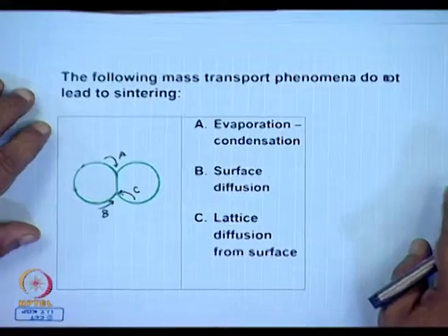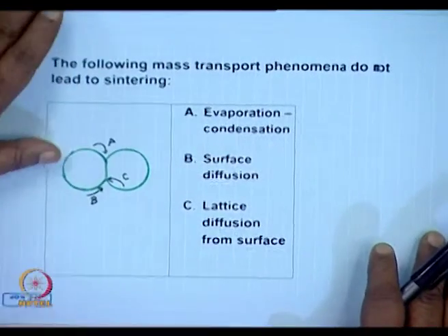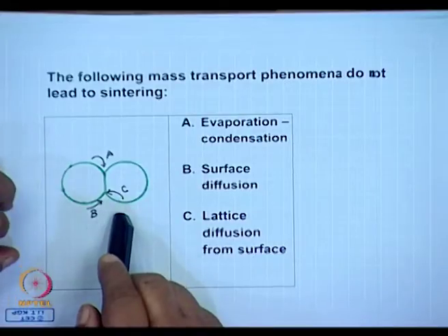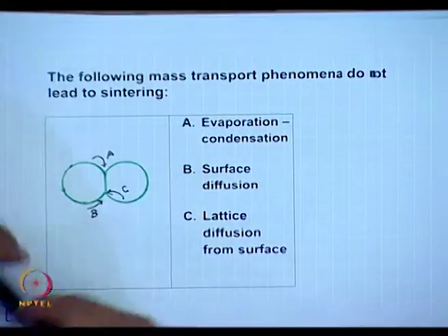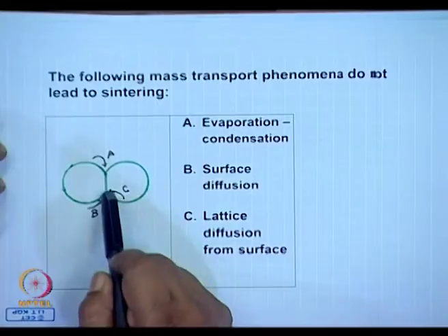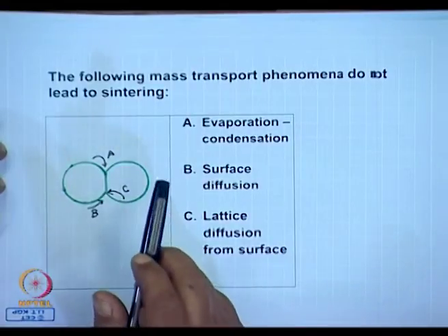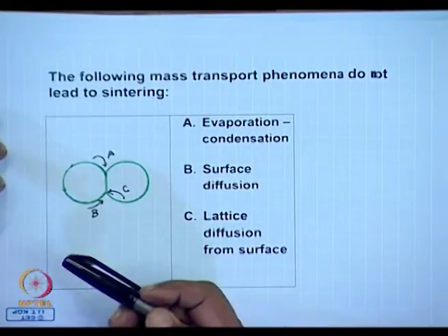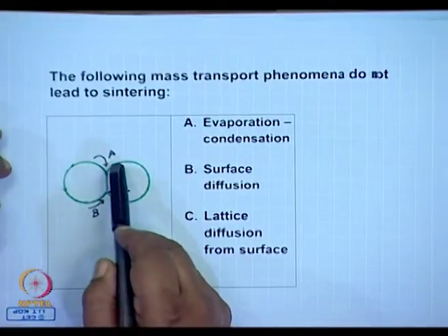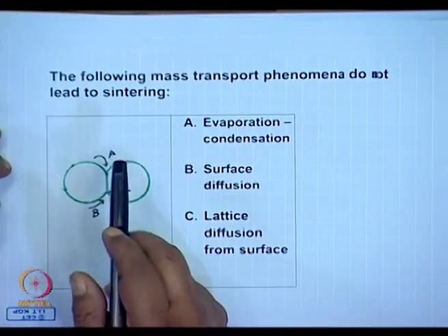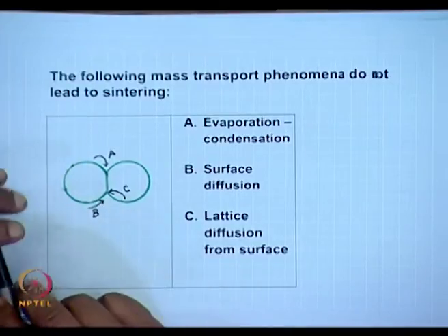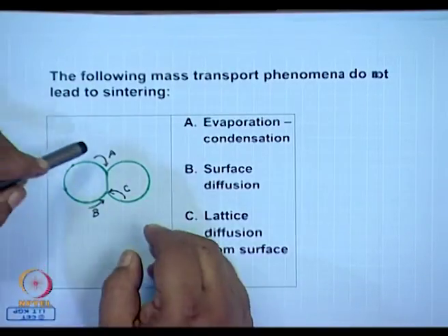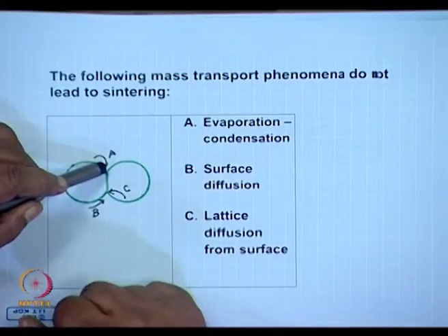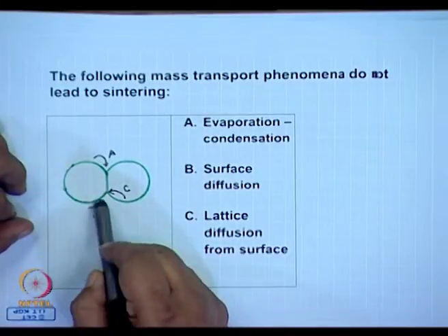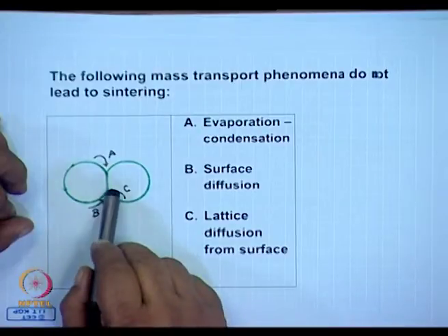Now let us take three mechanisms which do not lead to sintering. These are two particles in contact. There is a neck area where they have joined. The driving force here is to increase the area of the neck so that the free energy decreases. One of the ways that happens is evaporation condensation, surface diffusion, and lattice diffusion from the surface.